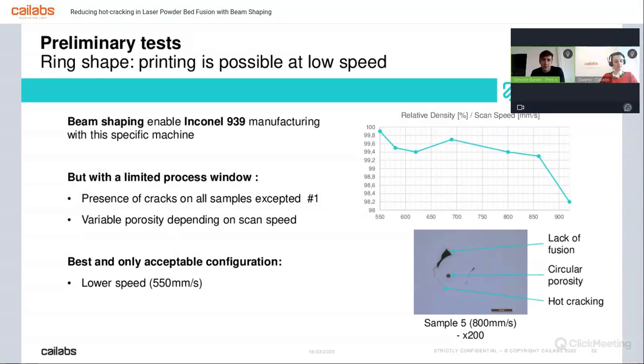The presence and the coherence of this secondary phase introduce the high strength characteristic typical of superalloys. The problem with additive manufacturing this kind of alloy is that if you continue to give energy to the system, the secondary phases grow, reaching a point where they are not coherent anymore, and so they are introducing stresses.